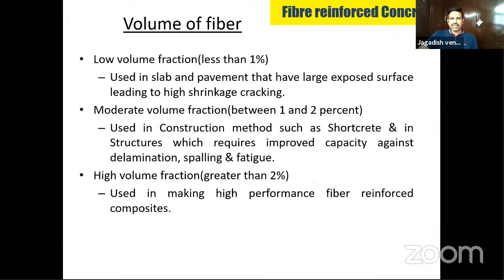1 to 2% we call a moderate volume. We use it for shotcrete applications, because when you do shotcreting, the material has to go and stick to the reinforcement, and the mortar or the material should stay together. So for these you need more fibers, and they also improve the capacity against delamination and spalling because the fibers hold the materials together. For high volume applications, particularly high performance fiber reinforced composites, we use high volume fractions, more than 2% by volume.